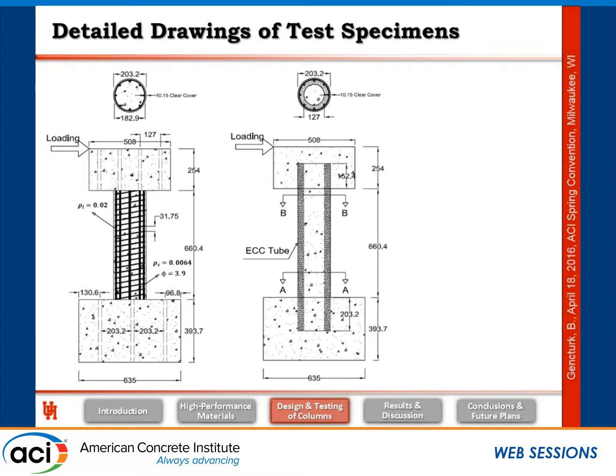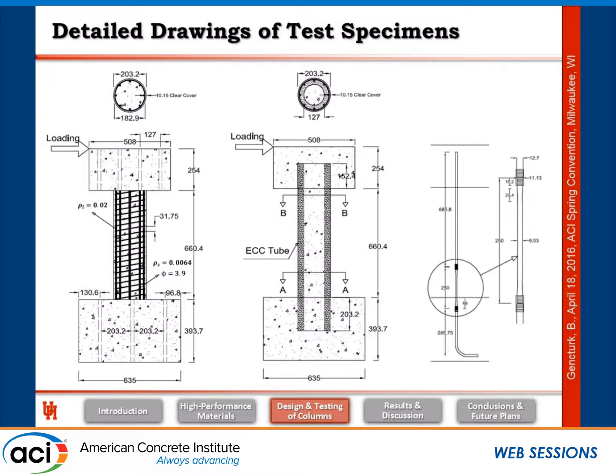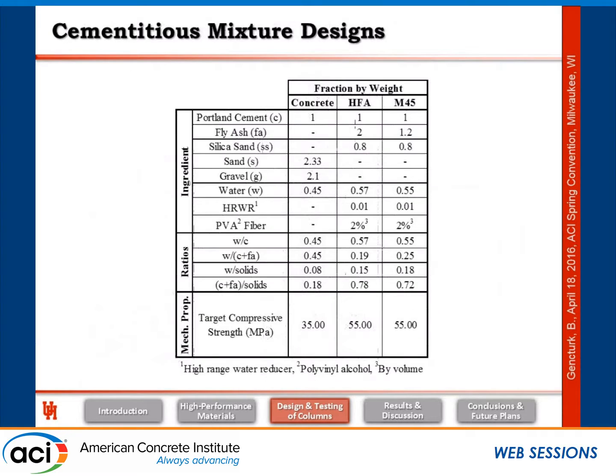This is 1.5 inches wall thickness, and then inside we fill with concrete. And then this is the detailing for the SMA in the plastic hinge region. We have a 3/8 diameter SMA bar, and these are coupled to regular mild steel rebar through some threaded couplers. Now, these are the ECC designs.